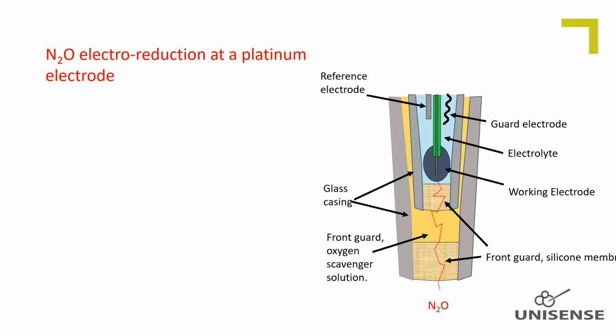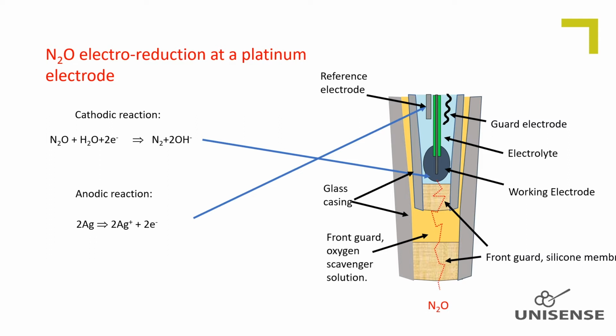If nitrous oxide is present, it diffuses through the membranes and the scavenging solution to the working electrode. The working electrode surface is a negatively polarized platinum electrode which catalyzes reduction of nitrous oxide. The electrons for the reduction are delivered from a silver reference electrode 10 cm away from the working electrode, but for sake of illustrating the principles, it is included in the schematic drawing of the tip. The current generated is proportional to the concentration of nitrous oxide outside the tip membrane, and as the current is very small, in the picoampere range, a high-quality amperemeter is necessary for amplifying such tiny current.